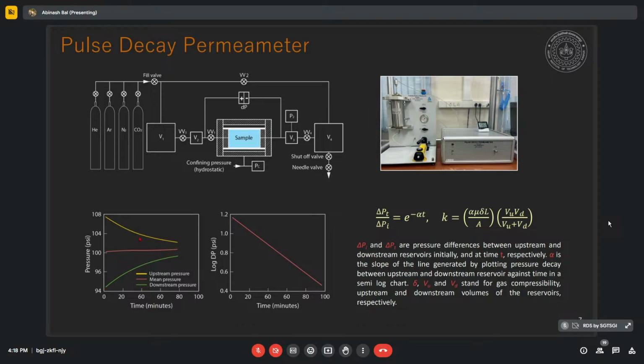So with time, when the gas flows from the upstream to downstream, this pressure decreases and the downstream pressure increases. From the amount of time it takes to get equilibrated, we estimate the apparent permeability of the sample at that condition, meaning at that confining pressure and at that pore pressure. Here the confining pressure is simulating the overburden pressure and pore pressure is simulating the reservoir pressure. And we use this formula, which is not the actual formula but the most simplified equation, to estimate the apparent permeability.